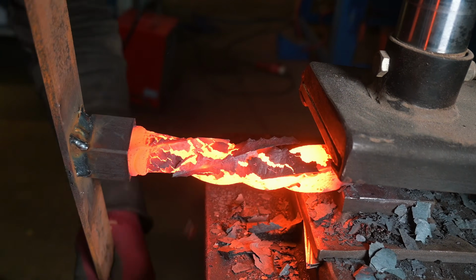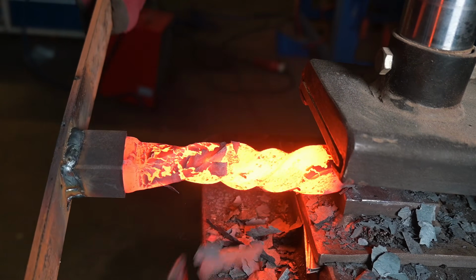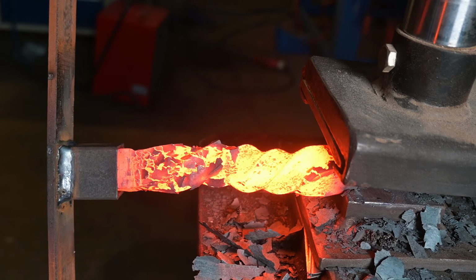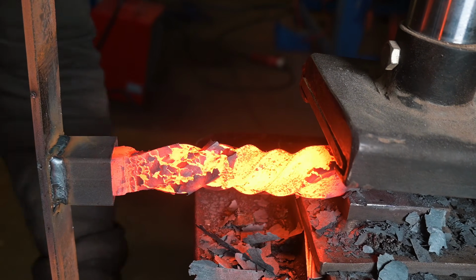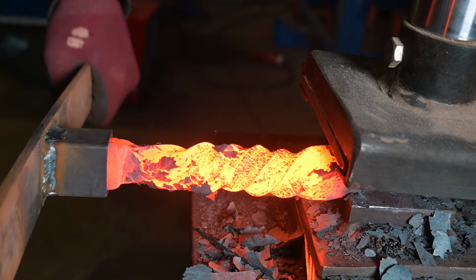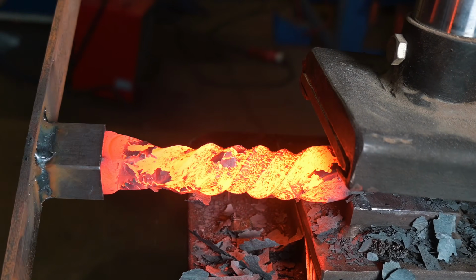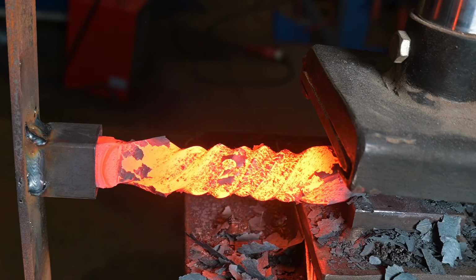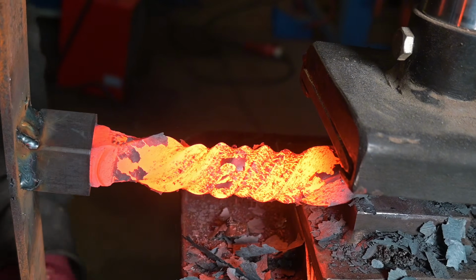After each twist I also covered that whole piece with flux so I don't get any kind of scale on it, because you can twist that scale into the steel, and you don't want to have that because this can lead to really bad failures during the heat treatment.